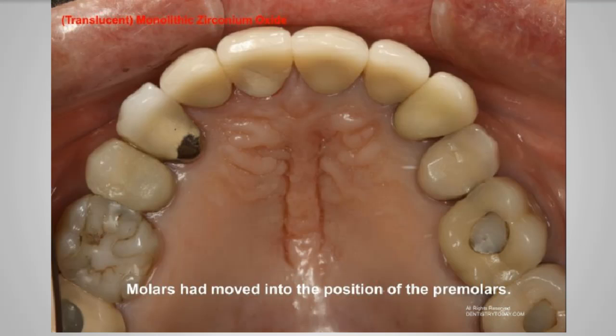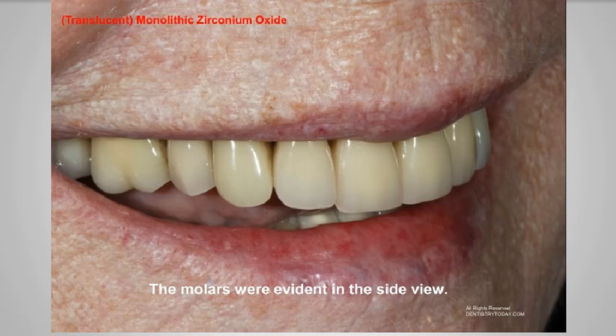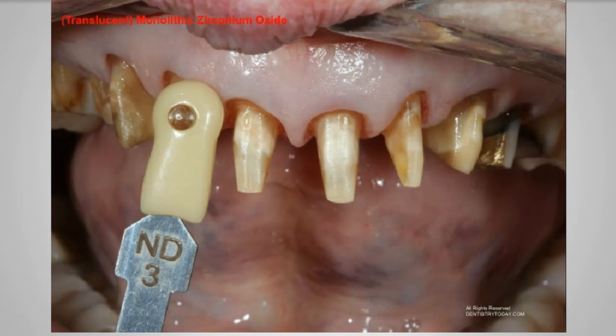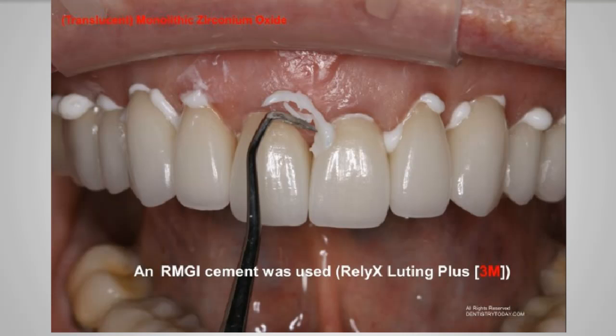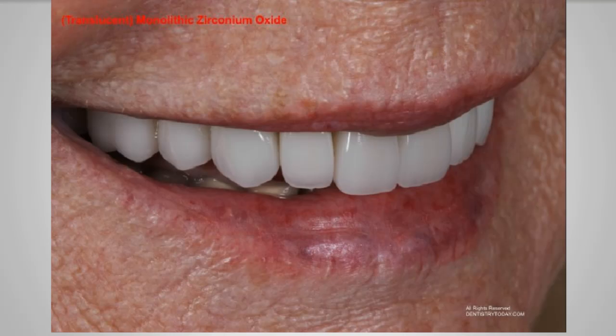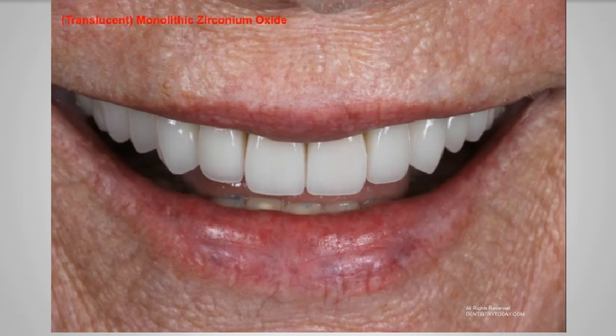So the molars had to be moved into the position of the premolars. The molars were evident in the side views, so they needed to be restored. Unfortunately, a lot of times we take old PFMs off and it shows the dramatic reduction that was required when these were done, maybe over-reduction. That's debatable here. We don't know the situation, often when we just take crowns off and look at somebody else's work. An RMGI, resin-modified glass ionomer cement, was used here. It was RelyX Luting Plus by 3M, peeled off easily and gives us a really nice result. And one of the reasons I show this is the first large monolithic zirconia case that was published in Dentistry Today.